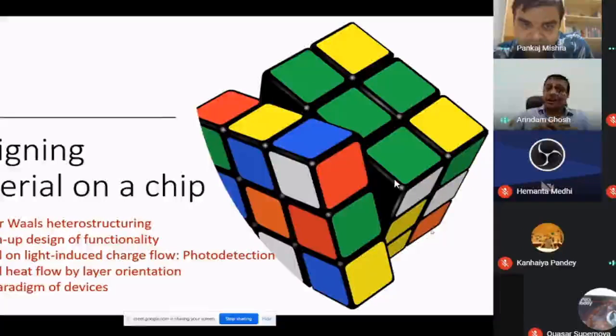So you can actually not only lay two layers at 0 degrees or 60 degrees, but you can do anything from 0 degrees to 60 degrees, because unlike graphene, the 0 degree and 60 degrees for the twisted TMDs are two physically separate entities, because the positioning of the molybdenum and the sulfur changes when it is 0 and when it is 60. And that makes a huge difference in its physical properties.